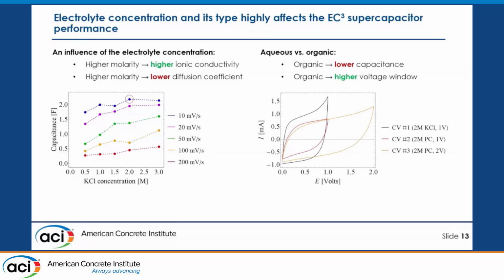Then when we compare, let's say, aqueous and organic solvents, we can see that, as I mentioned before, the area is indicative of the energy, how much we can store. We can see that aqueous solution, the black hysteresis here, from 0 to 1 volt can store slightly more energy than organic solvent, and this is because of diffusion coefficient. Nevertheless, we cannot exceed more than 1.23 volt for water not to deal with splitting of water into hydrogen and oxygen. So with organic solvents, we can reach higher voltage windows. So that gives us an advantage.